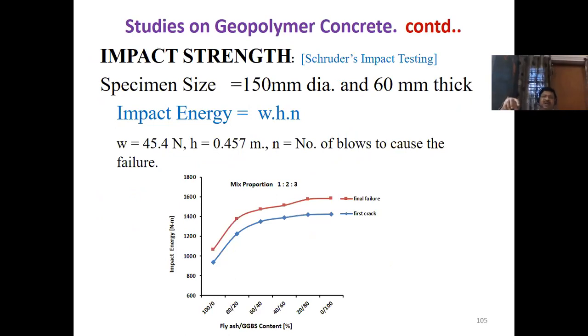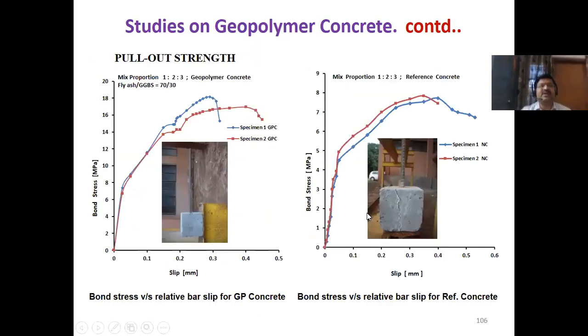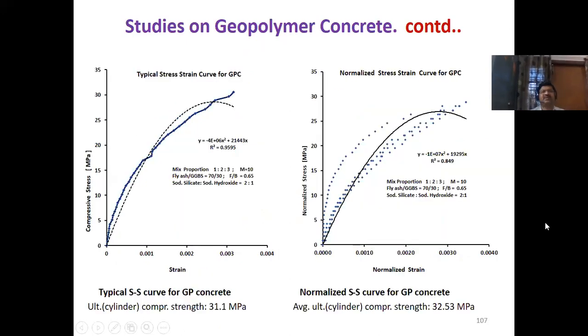We make a ball fall and see the number of blows that cause failure. It's around, see here, impact energy around 1600 Newton meter, right? It's very high. Of course, pull-out test also. Since it's a new material, we want to make sure that the concrete will have good bond with the steel. If at all we are using it as RCC, we have to insert the steel bars. So then there should be good bonding between the steel and concrete. So we wanted to check the bond with the pull-out strength. It's a little more than or equal to normal concrete. So nowhere is it inferior to cement concrete, right?